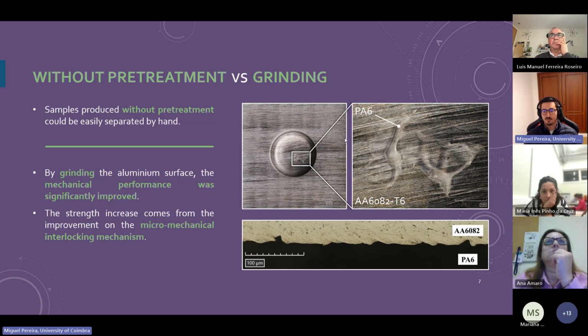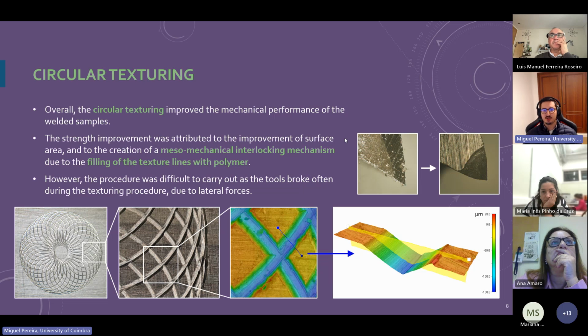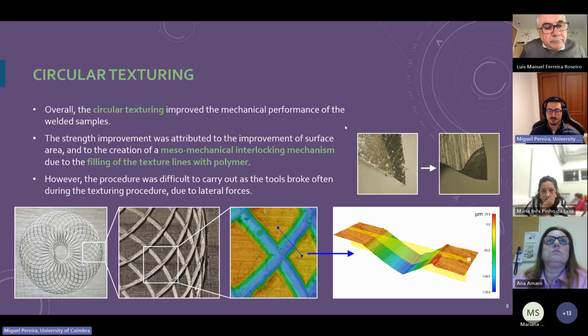But then we tested the circular texturing procedure, which is the process that leads to the more pleasant to the view results. And in this case, the circular texturing also improved the mechanical performance compared to the previous two. The improvement of mechanical performance is attributed to the creation of the mesomechanical interlocking mechanism, which in this case is due to the solidification of material in a larger portion of the texture. However, this procedure has a difficulty since tools typically break during the texturing procedure, as illustrated in this image.